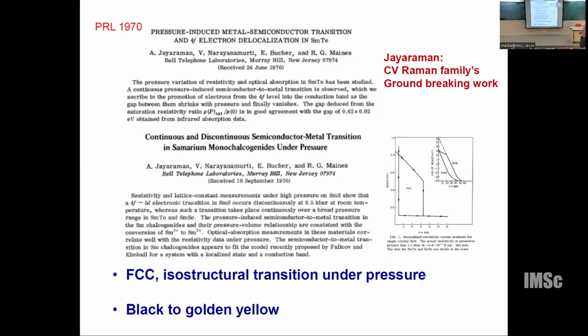The same thing can be induced by chemical doping. You put a little bit of yttrium in the samarium sulfide, and it becomes gold. You start with the black material and end up with a golden color. The paper was published in Physical Review Letters in 1970. This was again a landmark result in quantum physics. You could see the first order transition at 6 kilobar. But people, including Jayaraman's group, tried to study this material in more depth, and they found it behaves exactly like cerium under pressure.